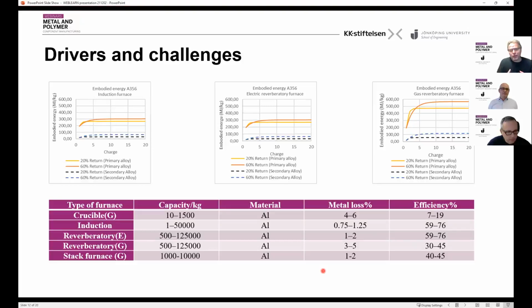And when we talk about material loss, you have a number of material that is being recirculated. If you take a virgin material and then you have a certain amount going back into the melt as in-house returns, the embodied energy goes up. And the same goes for carbon dioxide emissions. So you need to melt more material, and you sort of accumulate environmental load in the material. And of course, it's better to use recycled material compared to virgin material. But the principle is the same. If you recycle material, depending on how much you recycle and depending on what type of furnace you use, you have different effects. And it's always better with electrical drives than with gas-driven furnaces.